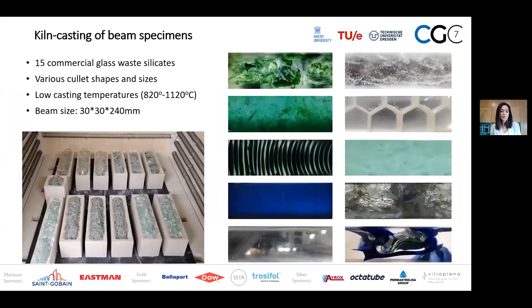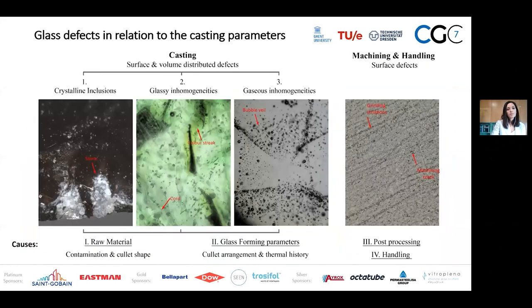So actually, what we do at TU Delft is that we take the waste that actually no one wants, and we recast it in our kiln, in order to understand the properties, but also the potential of becoming a new product. So we work with a range of different glasses from oven doors and car windshields and Pyrex trays, even the old television screens. And we try different shapes of cullets and different sizes, but also low forming temperatures in order to get interesting organized or random structures in our glass. And then what we do is that we study the defects and the mesostructures that we get in order to link them to the raw material that we used and also the casting properties that we have applied, so the thermal history, in order to understand how these defects are formed, but more importantly, how we can control them or even avoid them.